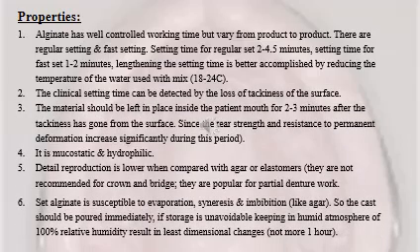Properties of alginate. 1. Alginate has a well-controlled working time but it varies from product to product. There are regular setting and fast setting. Setting time for regular set is from 2 to 4.5 minutes. Setting time for fast set is 1 to 2 minutes.